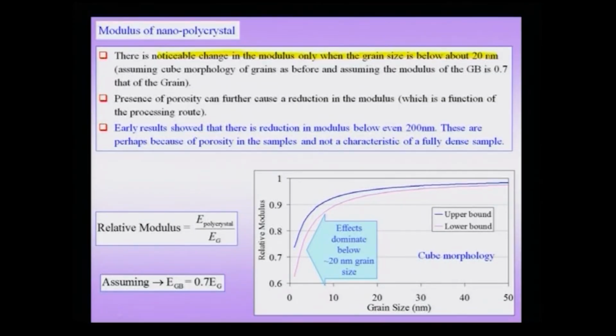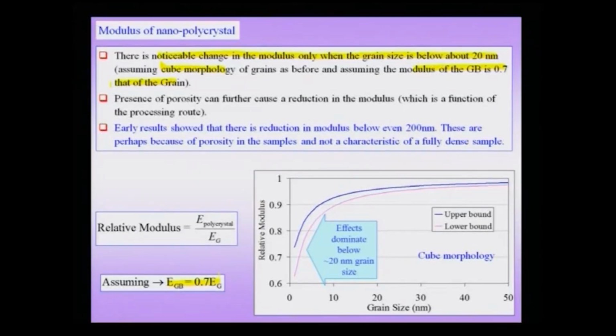And we continue the modeling which we did before. We assume a cubic morphology, and we also assume that the grain boundary has a modulus about 0.7 that of the grain. Here again, to really determine the correct modulus of the grain boundary is a difficult task. There is obviously no such single number which can be thought about, because the grain boundary itself, we have seen, is not a single plane, but it is a region in the material, and therefore, we have to assume some kind of a number, and for now we assume that the E grain boundary is about 0.7 E grain.